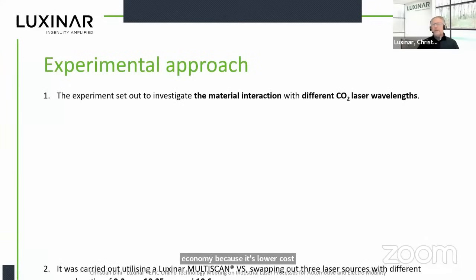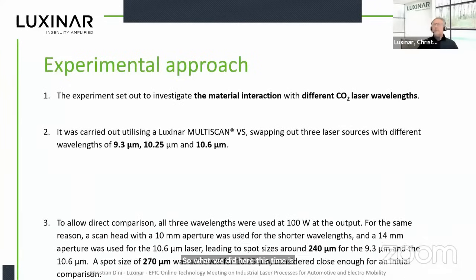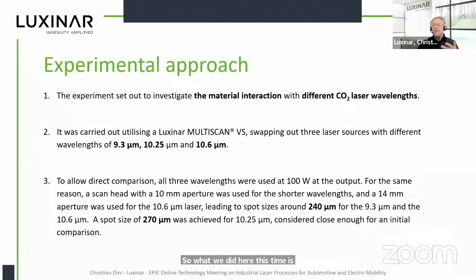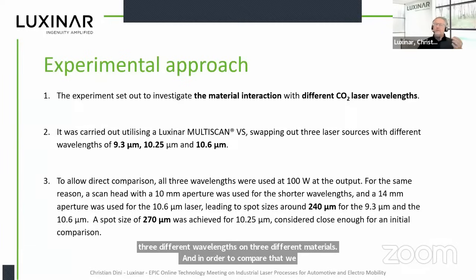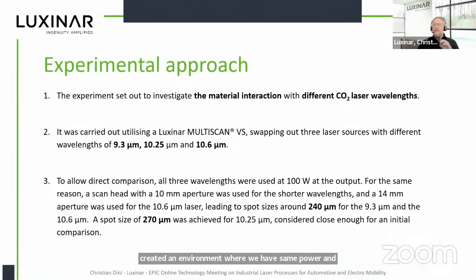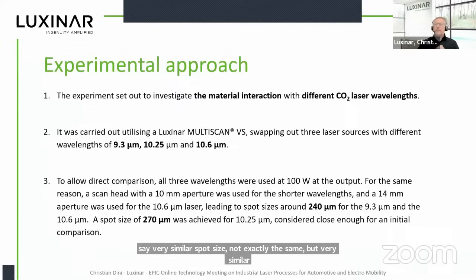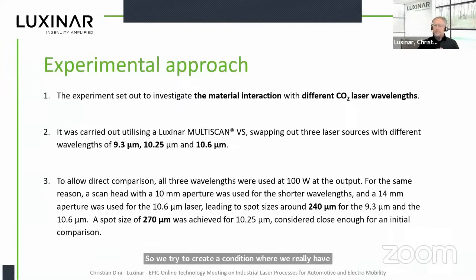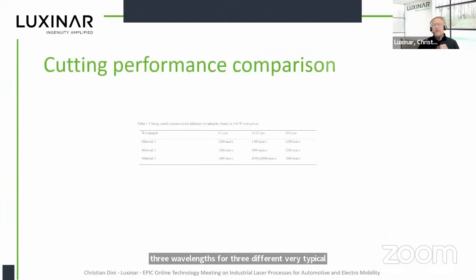So what we did here this time is we tried to compare 3 different wavelengths on 3 different materials. And in order to compare that, we created an environment where we have same power and, let's say, very similar spot size, not exactly the same, but very similar. So we tried to create a condition where we really have comparable data between 3 wavelengths for 3 different, very typical separator foil materials.